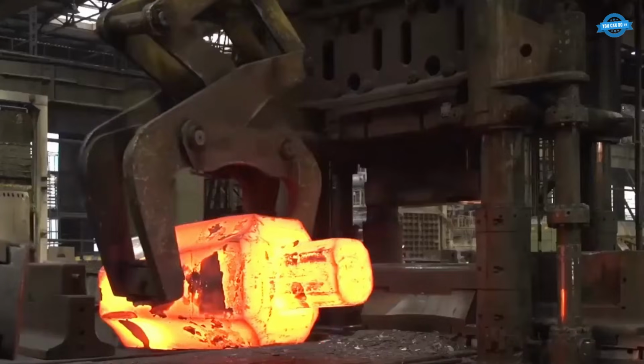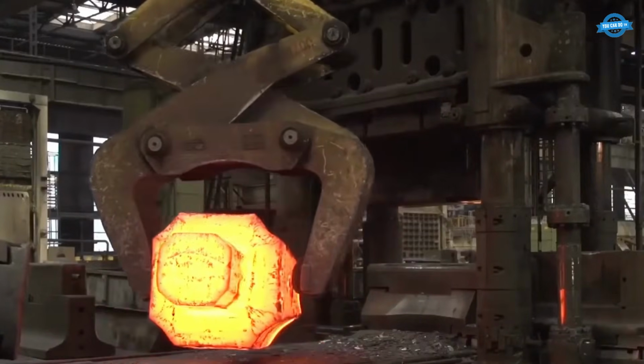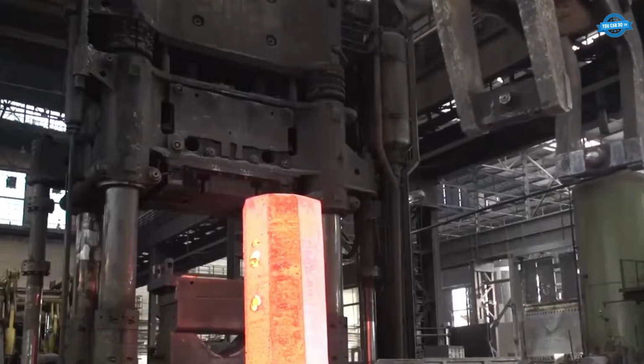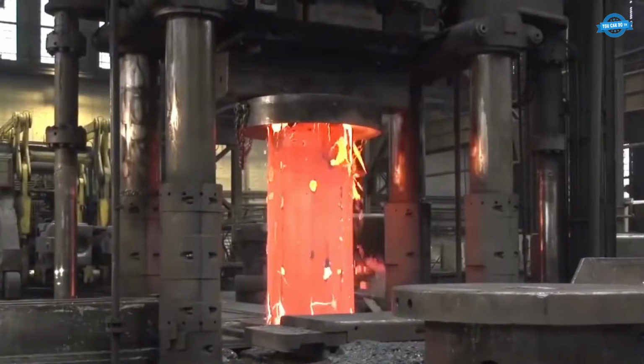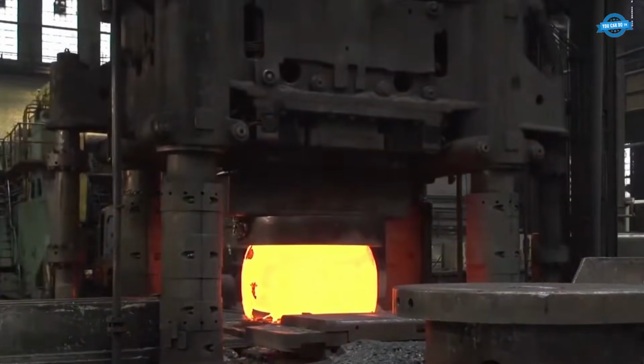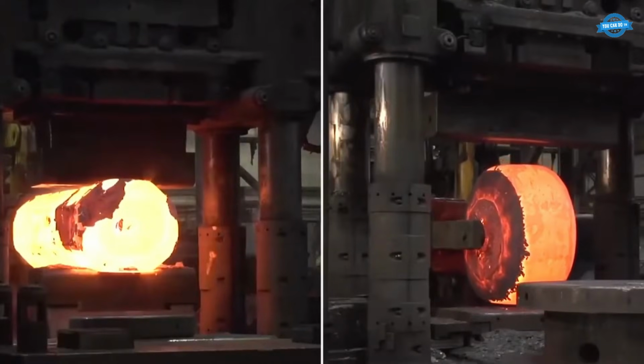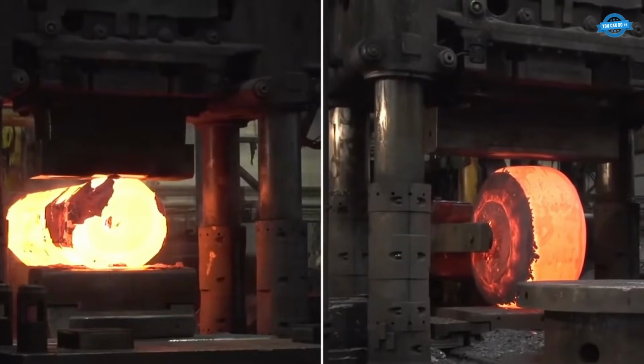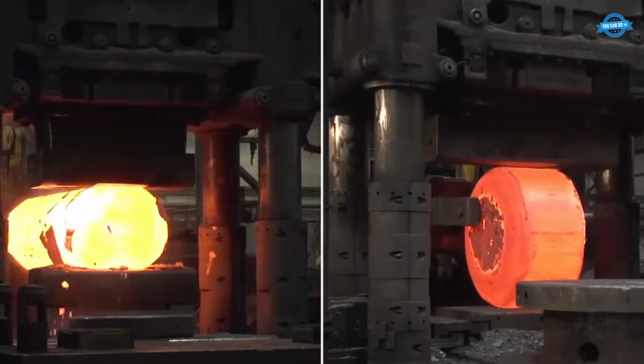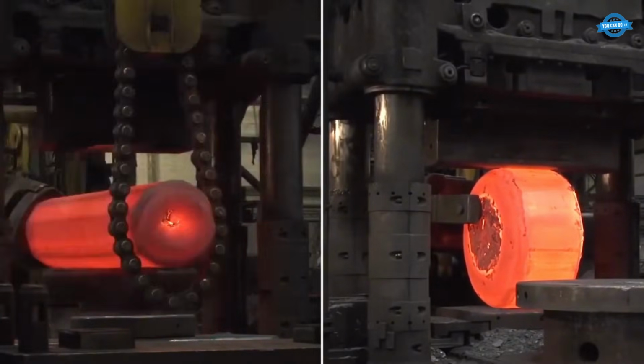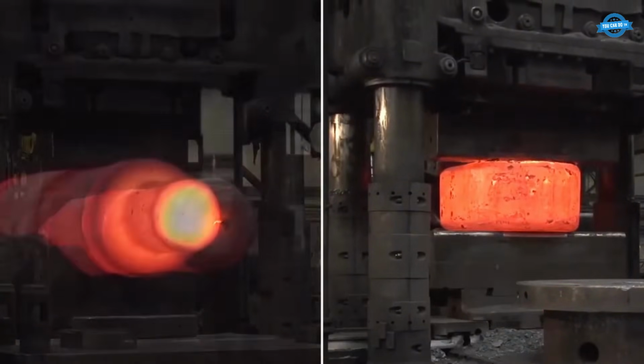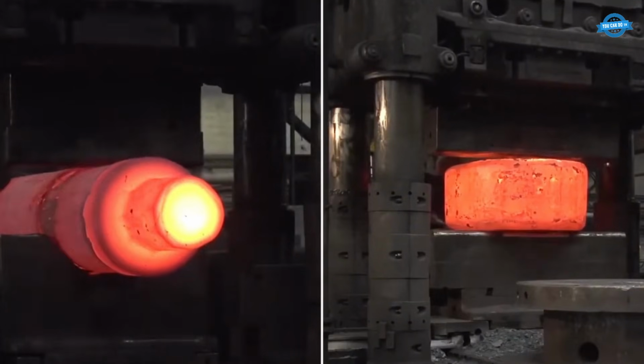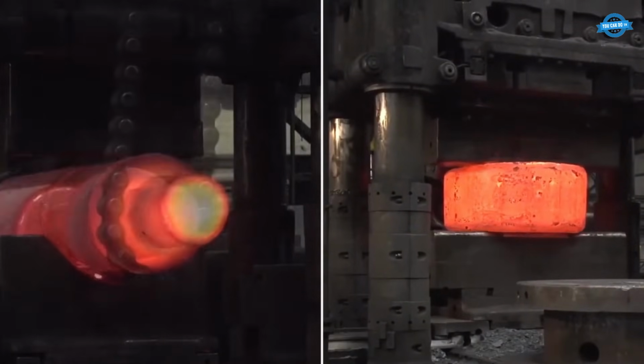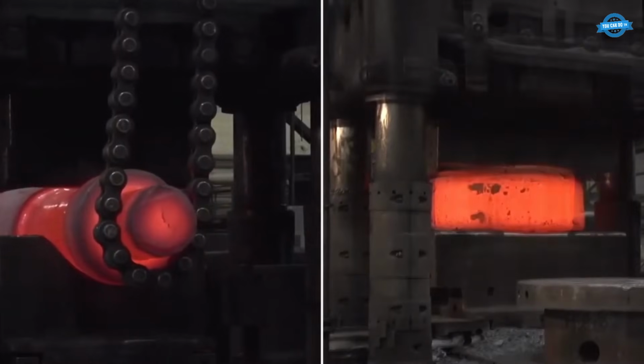Pre-forging heating raises the blocks to 1,200 degrees Celsius, preparing them for the meganewton press. Billets are positioned and forging begins, upsetting critical areas for optimal ratios. Turbine shafts and wheels undergo successive forging passes, guided by computer-controlled tools. Heat treatment follows, with vertical quenching in oil or water for shafts up to 8.5 meters long.